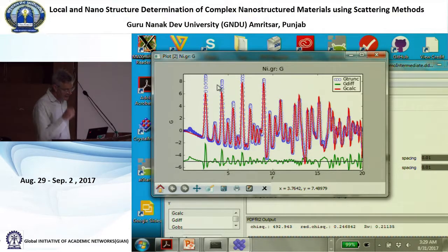So we actually need to refine QDamp. You need to gain a little bit of intuition with the program to know what to fit. But basically what's happening, this is my characteristic W or M. This means that the data are sharper than the model. And out here, the model is sharper than the data. The amplitude of the model is too high here, so the peak to valley of the model is higher than the peak to valley of the data. And the peak to valley of the model is too low down here. And in this region in the middle, it's fitting perfectly.